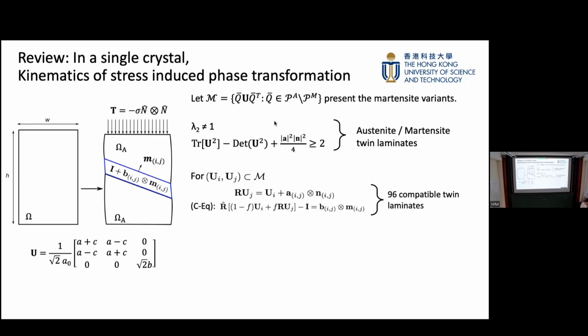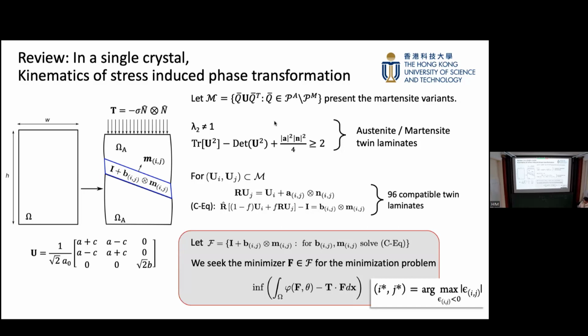And then we put them in a set, we call it a compatible twin laminate set. Those twins may be formed during the compression, and the minimizer is the one that minimizes the free energy minus T dot F, that is the mechanical power. This is equivalent to maximizing the compressive axial strain.